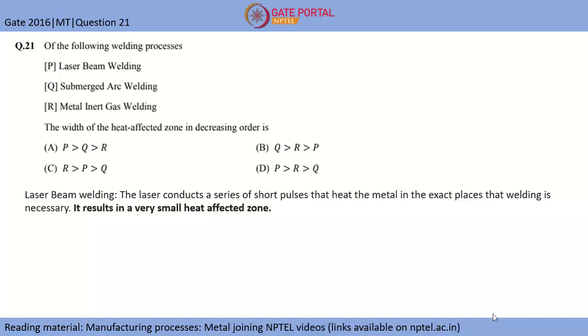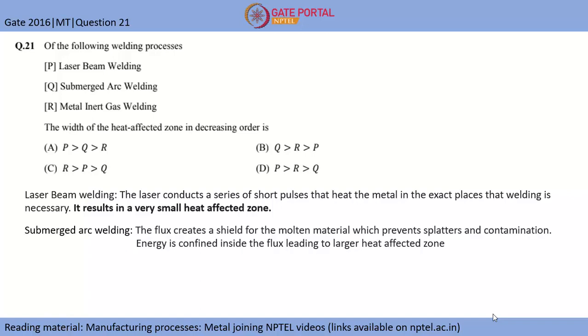In laser beam welding, the laser delivers a series of short pulses that hit the material in the exact places that we have to join. Basically, it is too localized to cause any significant heat affected zone. All the energy of the beam falls on the place where it needs to be joined, and the heat is extracted faster as it is very localized, so it results in a very small heat affected zone. So we should expect among all these processes that the least heat affected zone will be in laser beam welding.